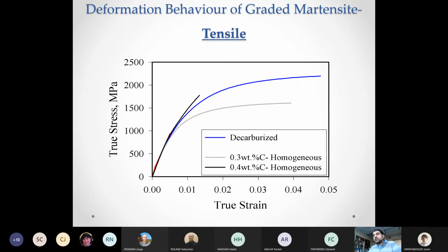Now, if we just pull this sample in a tensile test, we get the blue curve. So this is the behavior of this decarburized sample. And for comparison, I included here the behavior of the as-quenched sample with 0.4 carbon, so without any decarburization. And you could see the important improvement in ductility. The previous sample failed almost during elastic loading, whereas the decarburized sample, we can see clear evidence of yielding in